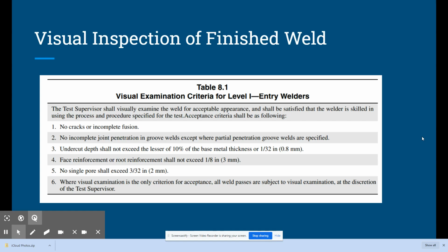And it says number 6, where visual examination is the only criteria for acceptance, all weld passes are subject to visual examination at the discretion of the test supervisor. And again, this is not the only criteria for acceptance. We're going to be bending these. So for a weld that you're using just visual examination and you're not doing a destructive test on it, then it's kind of at the discretion of the test supervisor, in addition to criteria 1 through 5.